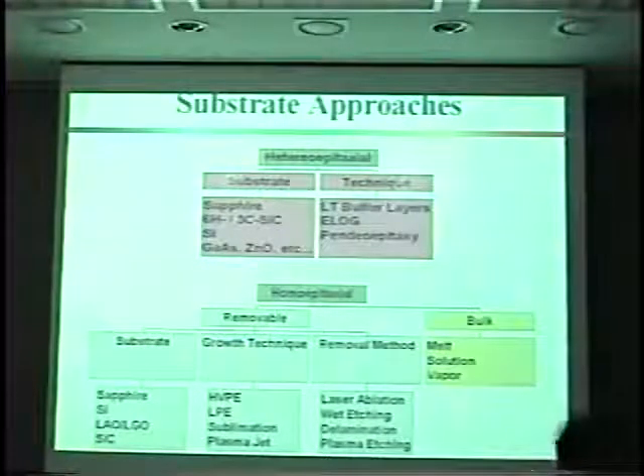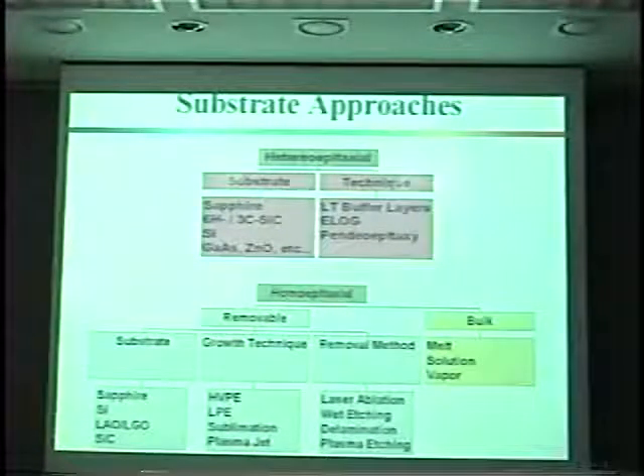All right, I'm going to move now and talk about growth on lithium gallate, LGO we call it. The idea here is to first grow a seed layer of gallium nitride onto LGO using traditional techniques, and then come back and grow very thick, a few hundred micron, gallium nitride by hydride vapor phase epitaxy, and then to remove the substrate.